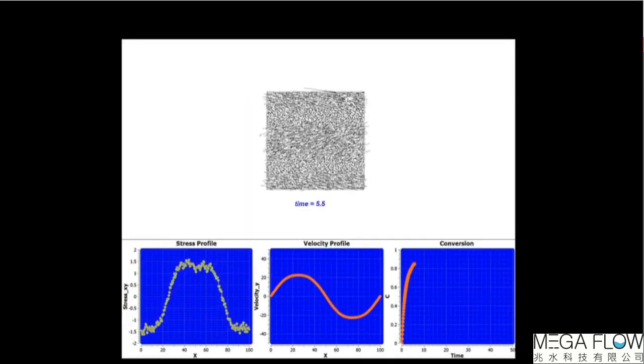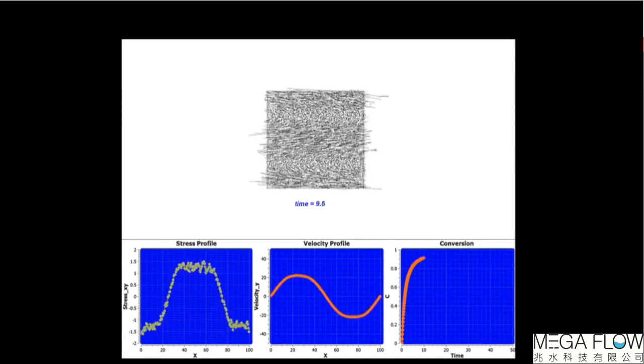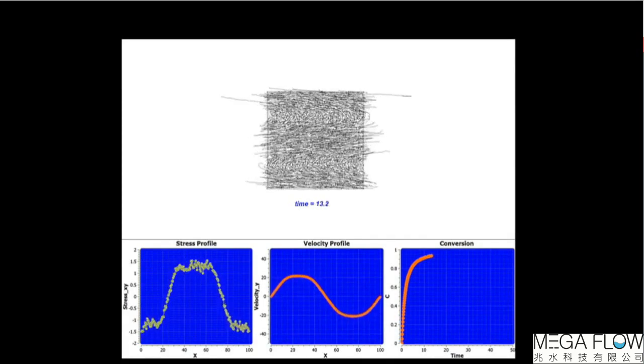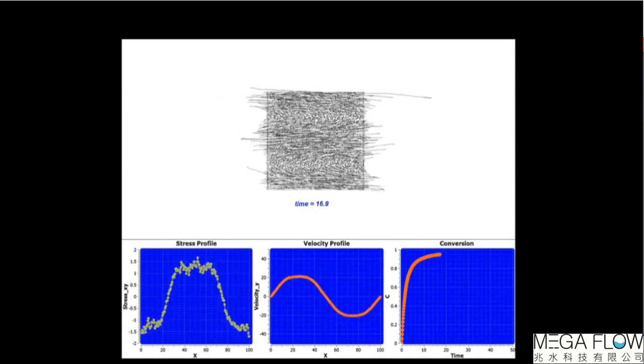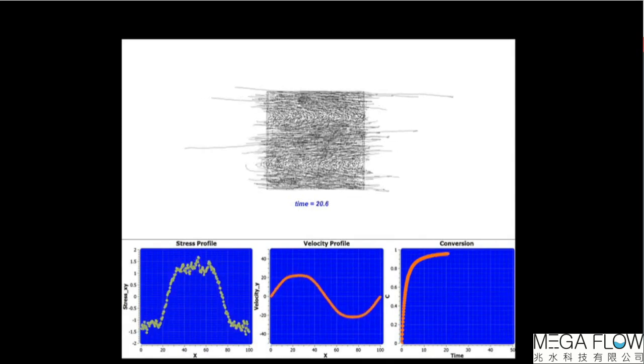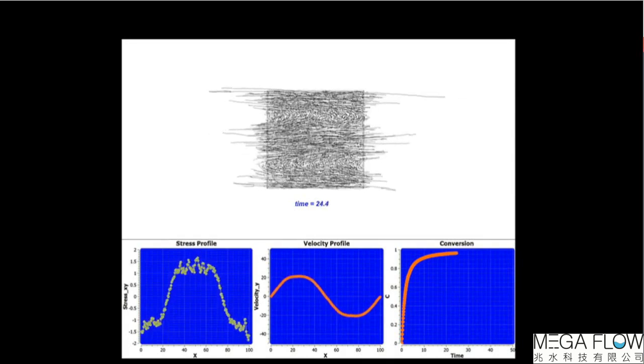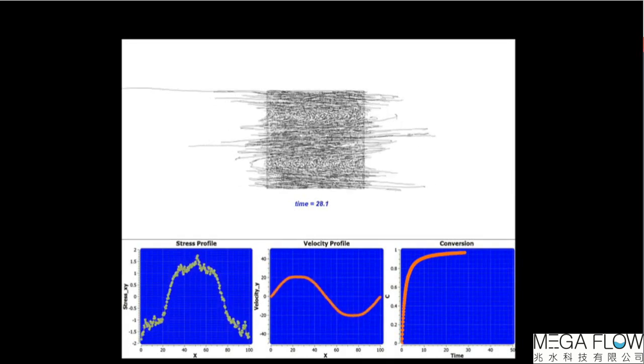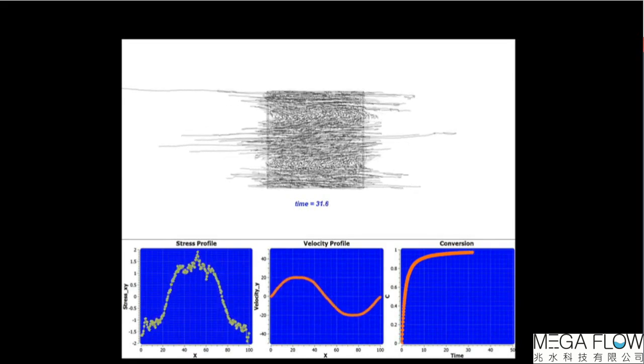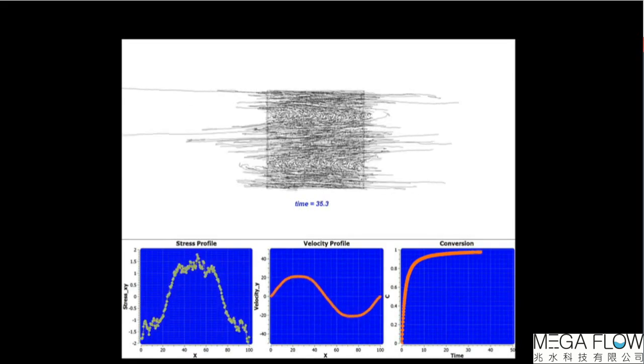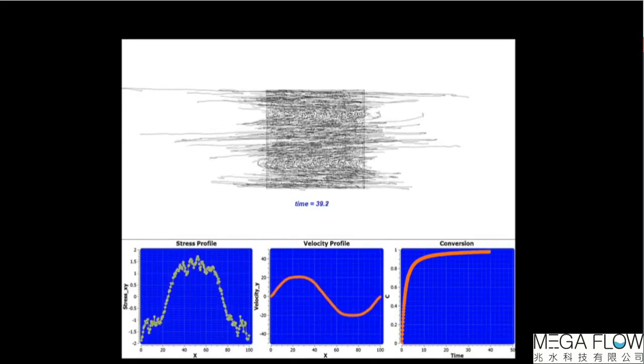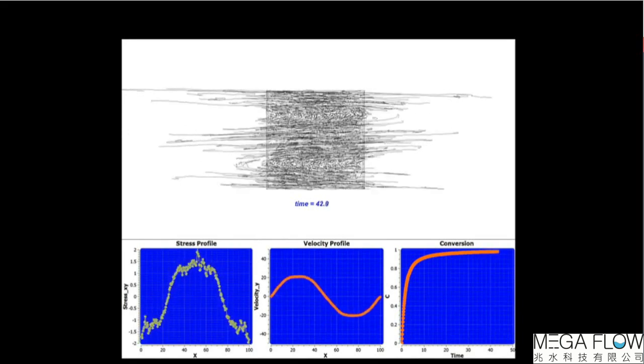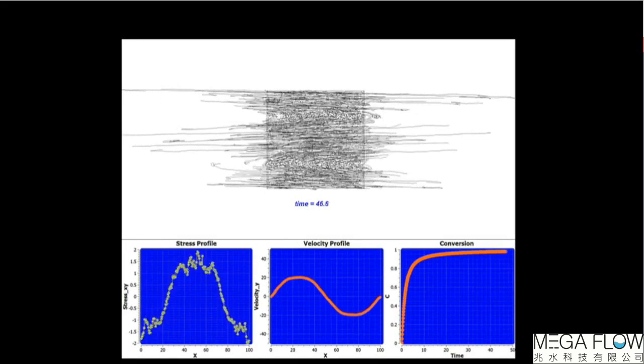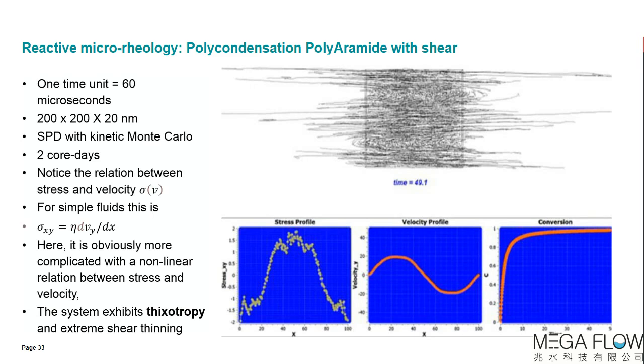So we have the conversion going on here. So that's increasing, longer and longer polymers are formed by the polycondensation, and the developing stress profile is in this direction, as I said. Initially it was really sinusoidal. That went very fast, but already after maybe 40–50% conversion, it started to become this much more flattened envelope here. And at the end, after 90% conversion, you will see you have very long polymers. And as in polycondensation, this is very heterodispersed. You see here these long polymers, but you also have much smaller polymers.